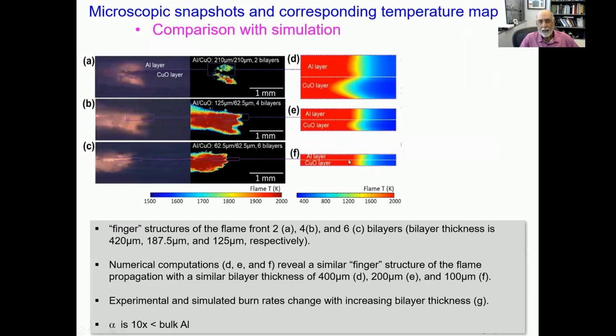And we've modeled this, and I don't want to get into the model, but again, to show this fingering behavior, the model does in fact show more or less a fingering type behavior between the copper oxide layer and the aluminum layer thermally. And that's because this copper oxide layer is endothermic because it's losing oxygen. The exothermicity is occurring in the oxidation in the aluminum layer.